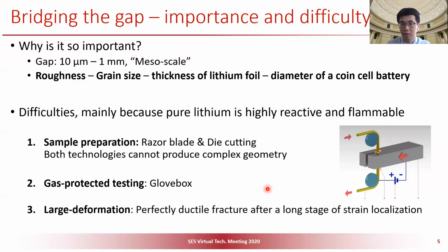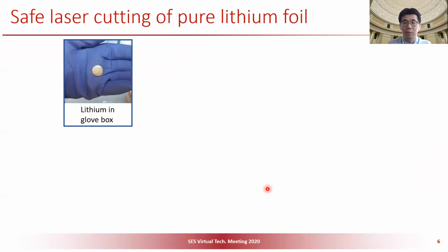And the last difficulty that today I will point out is the large deformation of pure lithium. According to our test results, you will see that lithium is really a perfectly ductile material. So it will be very difficult for testing and for modeling. Starting from the first challenge, we developed a very safe laser cutting of pure lithium foil.